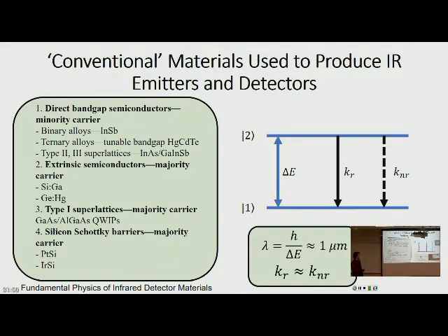And you also want the radiative and the non-radiative relaxation between those two states to be roughly the same order of magnitude if you're looking for efficient absorption or radiation. Why do you need that for efficient emissions? I didn't put it in here, but for emission, PL quantum yield, which is a measure of how efficient it is, is KR over KR plus KNR. So if they're roughly about the same, you're going to get like 50% luminescence quantum yields. So you want them to be on roughly the same order of magnitude at least.